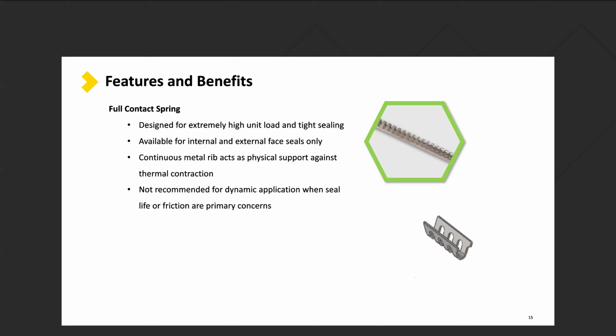Maudlin manufactures this spring in straight lengths. The spring then has to be rolled to the basic diameter of the seal that it's going to go into. It is then installed in the seal, and in most cases has to be welded well inside the seal jacket. There are exceptions to that in very, very large seals where you might be able to stretch the jacket over the spring once it's welded. But I would say 10 to 12 inches and under, generally speaking, you have to cut the spring, roll it, install it into the seal jacket, and then weld it in place. And Maudlin can provide the weld tabs and give you some recommendations on process to do that, but we don't roll or weld those springs in-house.